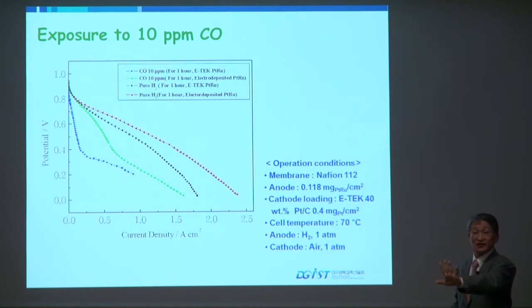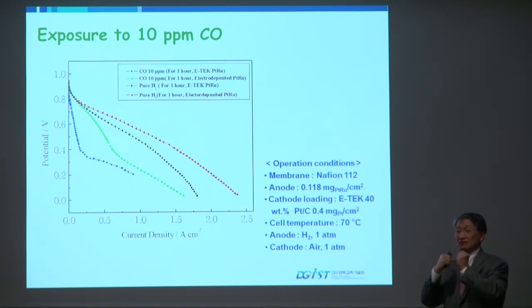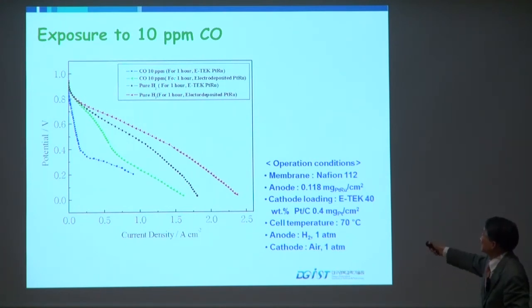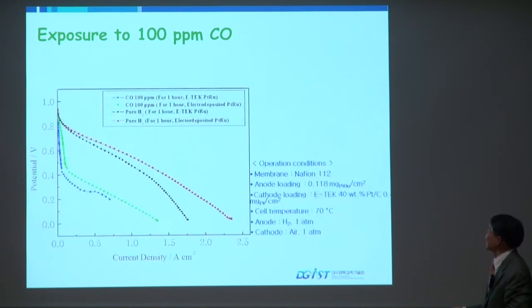Then we expose this to hydrogen containing carbon monoxide. One of the big problems in fuel cell applications, especially in DMFC, is the poisoning of platinum with carbon monoxide. The binding of carbon monoxide to platinum is so strong that the catalytic site is dead after it is exposed to gas containing carbon monoxide. This is original. This is 10 ppm carbon monoxide. And this one, the original ETEC catalyst, reduced to this. And when we increase to 100 ppm, of course, both are almost dead.